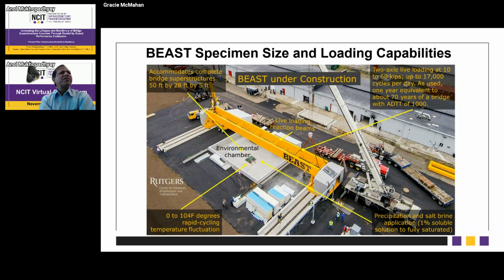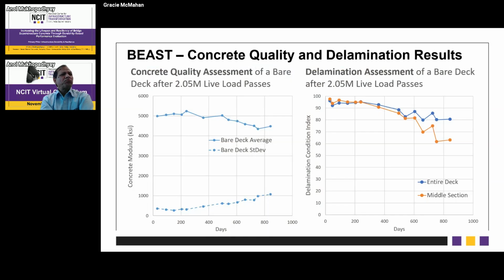Okay, so this is the BEAST. They actually place a deck, 50 feet by 28 feet, 5 feet thick, inside this environmental chamber, and it simulates the load, which is around 17,000 cycles per day. It's a very accelerated load testing. They apply brine salt and also freeze-thaw cycles. So it is under simulated conditions, and they try to understand the behavior of the deck within a small period of time, like within 2 years. Can you go to the next?